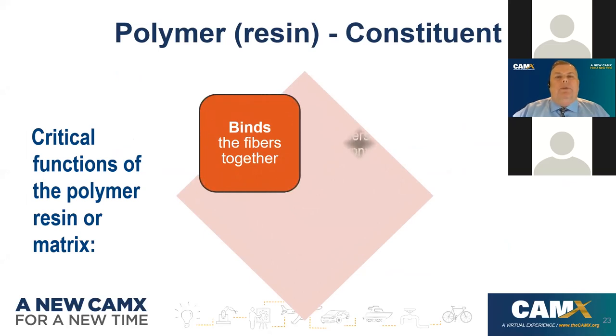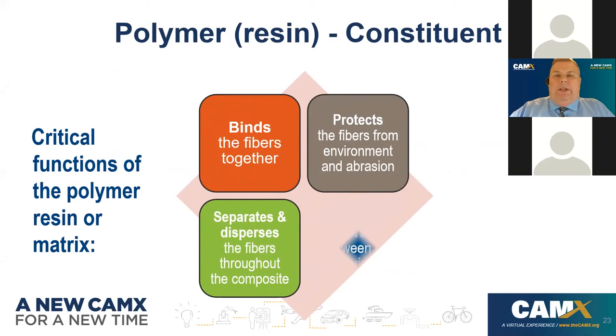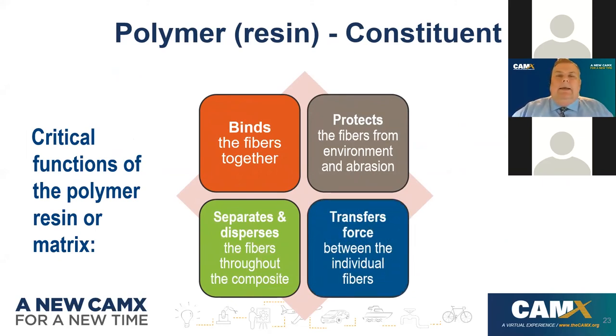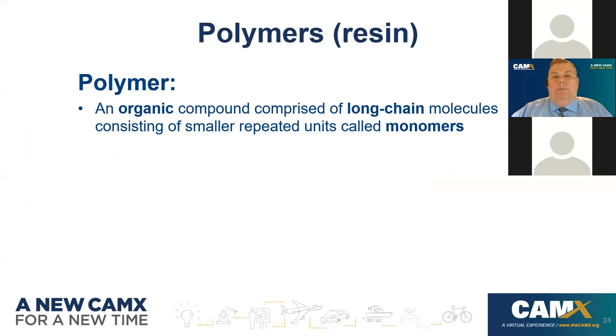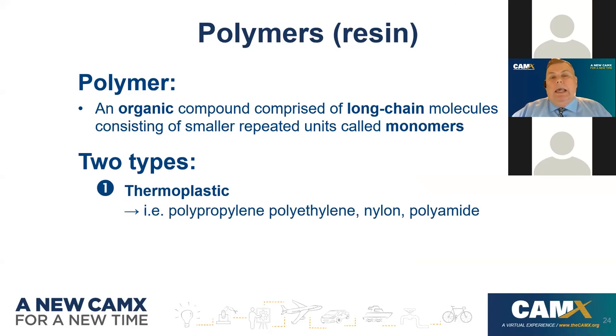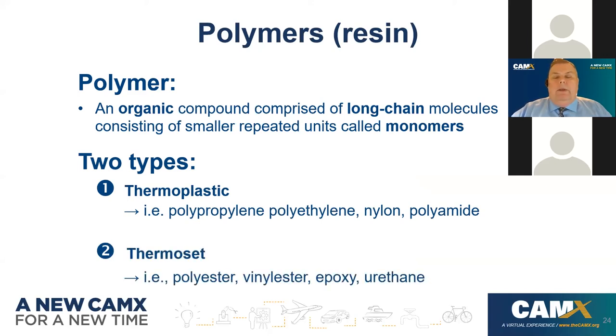The critical functions of a polymer are to bind the fibers together, protect them from environmental attack and abrasion during manufacturing, disperse fibers uniformly throughout the composite for even load distribution, and transfer forces between individual fibers. A polymer is an organic compound comprised of long-chain molecules. There are two types: thermoplastic (polypropylene, polyethylene, nylon, polyamide, and others) and thermoset (polyester, vinyl ester, epoxy, and urethane).